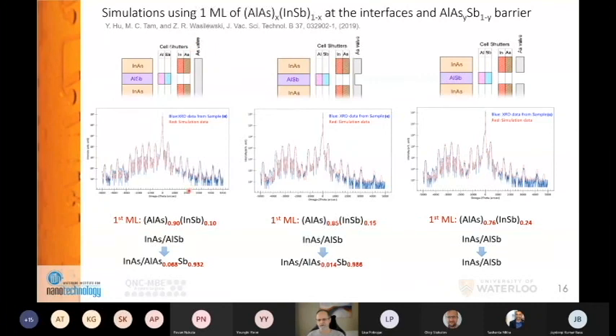if we keep the arsenic valve open, the interface monolayer, the interface between the indium arsenide and aluminum antimonide, is 90% aluminum arsenide bonds. However, and this was a new finding, which somehow was disregarded so far, the aluminum antimonide is no longer aluminum antimonide, but it has up to 7% of arsenic in it. So that, I should say, goes beyond what has been detected with the TEM. Maybe it wasn't looked for really.